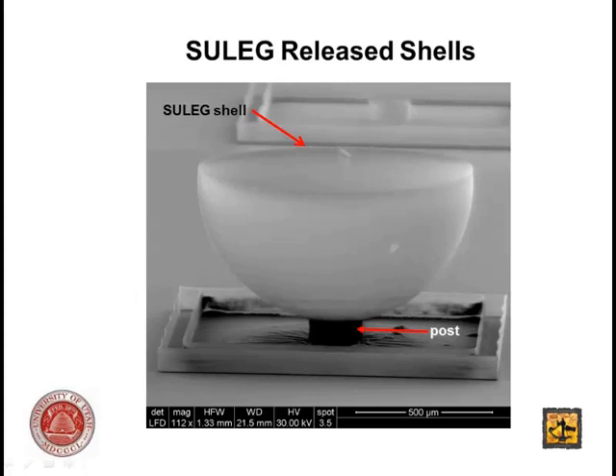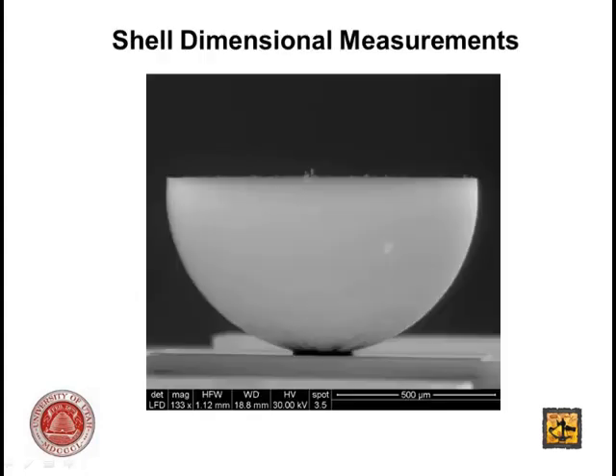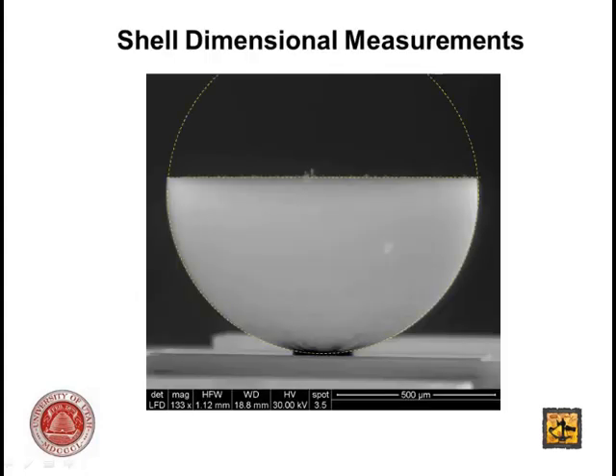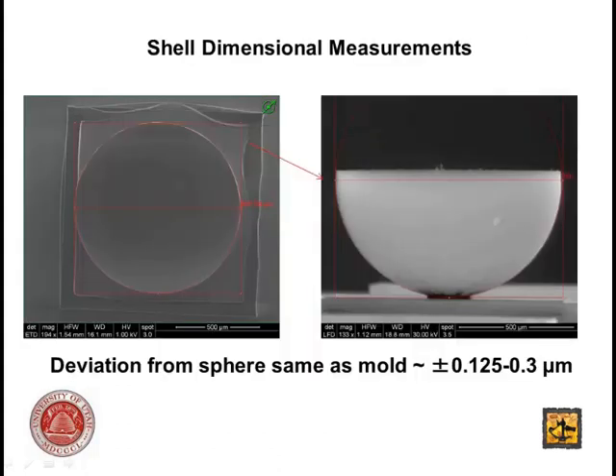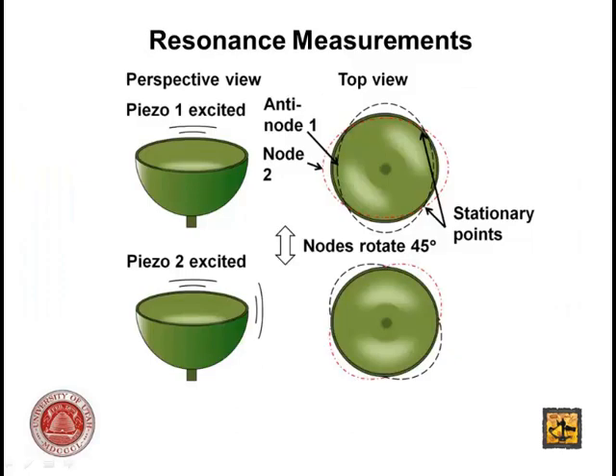Now, the nice thing about this type of structure is that it has very accurate dimensions. We actually compare this to a perfect sphere. As far as we can tell, we have a deviation of about 0.3 microns within our measurement capability, which is about the spec of the initial mold. So those are the shells that we build. We also have a little bit of side roughness on the edge, which is something that we are fixing for our sponsor because the sponsor wants it.